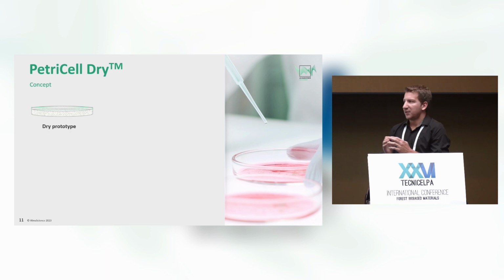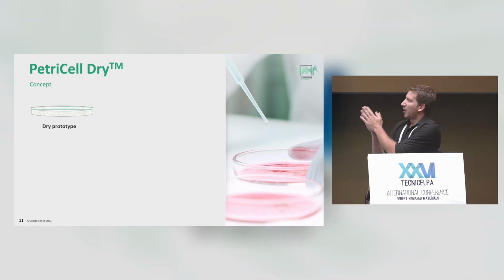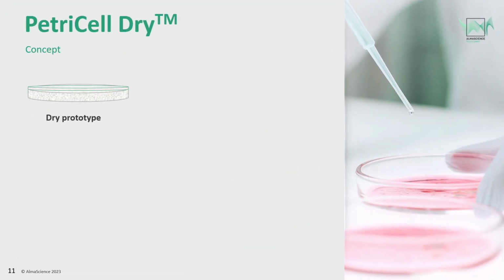So in the end, what we have is this: a dry prototype, which has the dry hydrogel on the surface with the base paper below. After we add water, this hydrogel will absorb the water and we will have a similar consistency to the agar-based Petri dish. Then we can do our inoculation on this device and incubate it and see how this microorganism will grow.